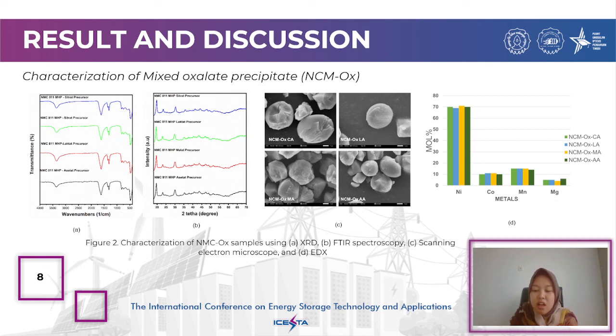For the particle morphology of the as-prepared NCM oxalate sample, it appears that the different types of organic acid used during the leaching process produce different types of morphology. NCM oxalate from citric acid, lactic acid, and acetic acid samples exhibit near-spherical shapes and coffee bean-like morphology. On the other hand, NCM oxalate from malic acid has a contrasting morphology compared to the other three. It has a rod-like spherical morphology. The sample treated with citric acid has the largest particle size, while the sample treated with acetic acid has the smallest particle size.